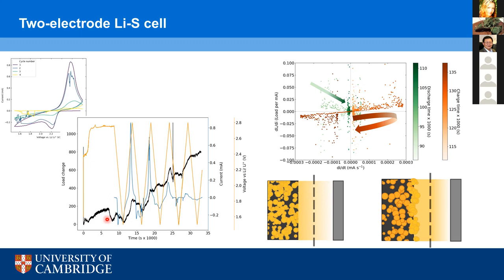Looking at the scatter plot in the top right, this is for the first discharge and charge cycle. During the first discharge, the pressure change with changing current is positive. This is theoretically associated with the formation of lithium sulfide, which has a higher volume than the precursor, elemental sulfur. Then during the first charge, the pressure remains positive initially and then decreases.